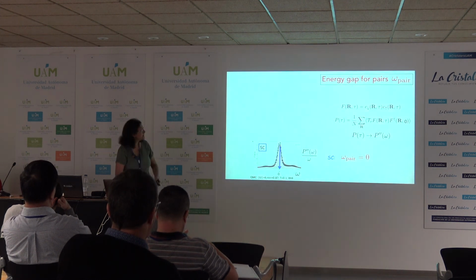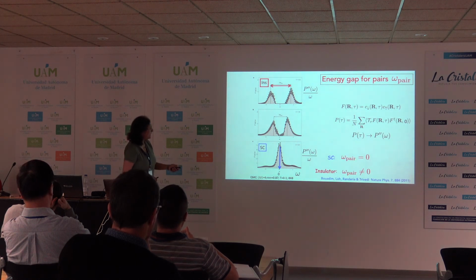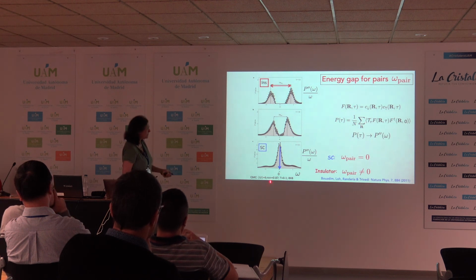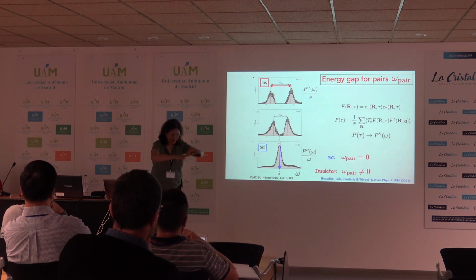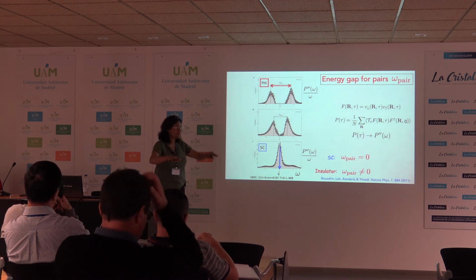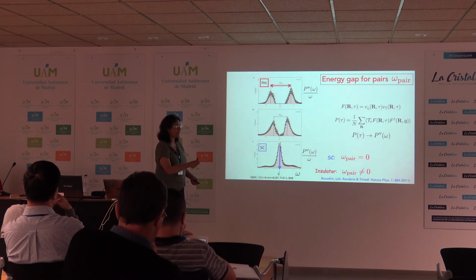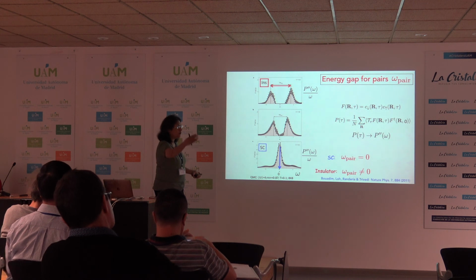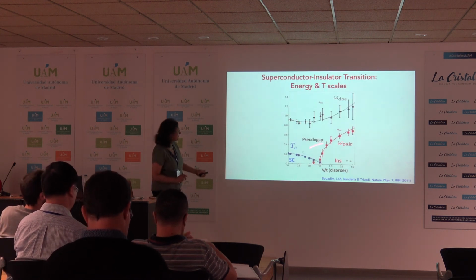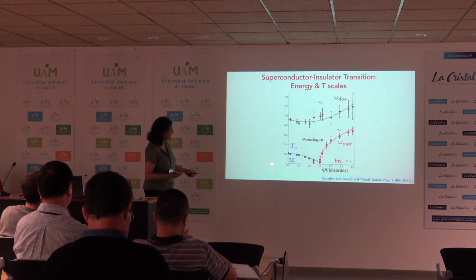Something like this. Here we have a pairing, sorry, a CC object, a pair object at time equal to 0. We create a pair and we destroy it at some later time and we get that spectroscopy. If it's coherent, you can put a pair at 0 frequency because your underlying state has no phase fluctuations. But if there are phase fluctuations, then it costs some energy to add the pair. Another way, you can convert this energy into a time scale. Here the time is becoming infinitely long. So the inverse of this is a time scale for coherence. Here it is infinitely long, and here there's a time scale which is diverging at the transition.